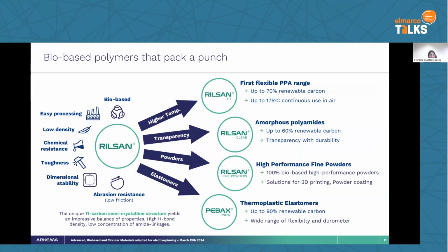So as we produce the monomer, then we can play with the chemistry. We are a polymer producer. So either we can have our polyamide 11, as I said, Rilsan, or we can play with the monomer, associate it with other monomers, other functionalities, and we can have a very broad product portfolio from some PPA, some Rilsan HT (high temperature), some amorphous and transparent polyamide, some powders, and TPE. I cannot disclose everything, but just to share that you have a very broad product portfolio, bio-based, with very specific properties adapted to many different markets.